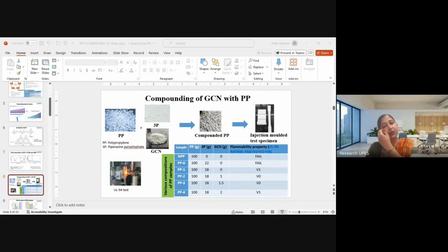So when we did the UL94 test for these compositions, we found that only PP2 and PP3, in which GCN was added in 1 gram and 1.5 gram, passed that rating.